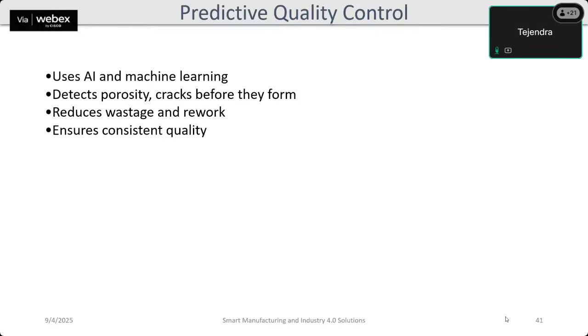Predictive quality control could be a game changer in WAM, as it helps to prevent defects rather than just detect them after the complete part or the complete object has been built. The process works by combining sensors with AI. The sensors continuously capture information about the melt pool size, the bead geometry, the temperature distribution, or even the acoustic signals during the deposition.